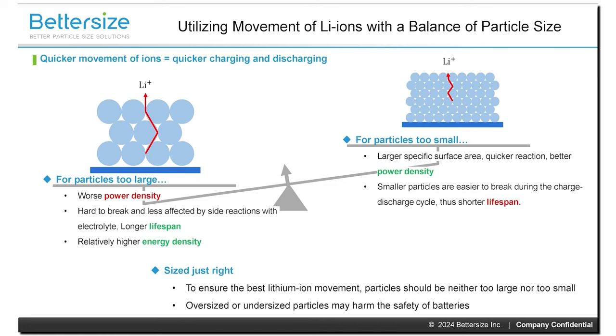We can affect characteristics of lithium-ion battery by balancing particle size. For example, with respect to electrochemical reaction kinetics, smaller particle sizes generally lead to faster lithium-ion diffusion and shorter diffusion pathways within the electrode material. This results in improved electrochemical reaction kinetics, including faster lithium intercalation and deintercalation rates, and as a result, batteries with smaller particle sizes typically exhibit higher charge-discharge rates and improved power performance.